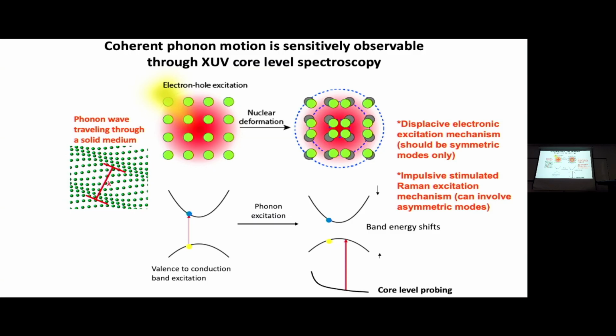So now what about the lattice? Initially, let's say we have a perfect lattice. But then we excite across a band gap, and that changes the potentials. So maybe the potentials will have a smaller gap, and they may be distorted in some way. And the lattice will now have to respond to that change, that the potential abruptly changed.